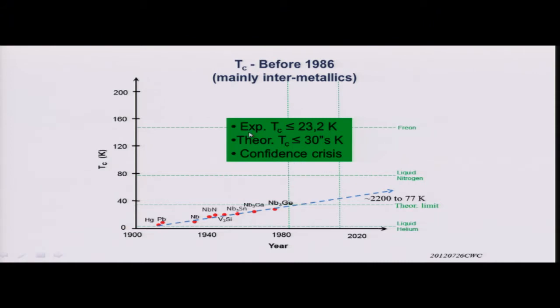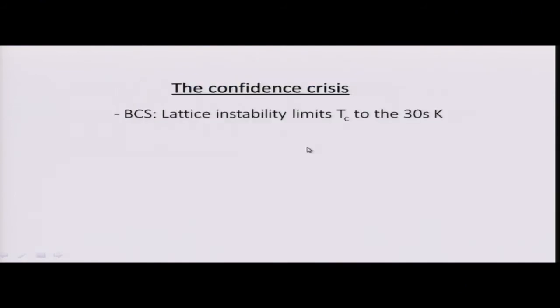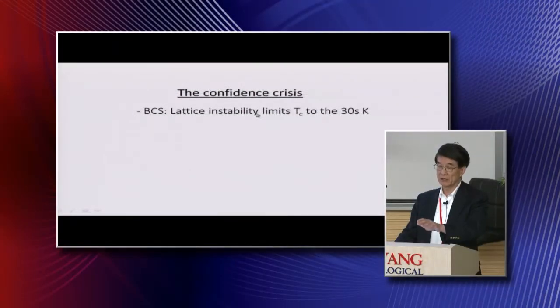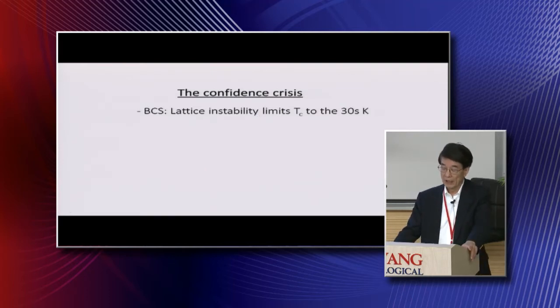And it turns out experimentally, people couldn't get it so high. The highest experimentally reached temperature is 23.2 degrees. And theoretically, people predicted the 30s should be the limit. So the most serious crisis at that time is the so-called confidence crisis. Then we looked into the cause of the confidence crisis, because basically the major thing is lattice instability. As I mentioned before, to get strong electron-phonon interaction, the lattice has to be soft. When it softens to such an extent, the lattice collapses. That's catastrophic instability.